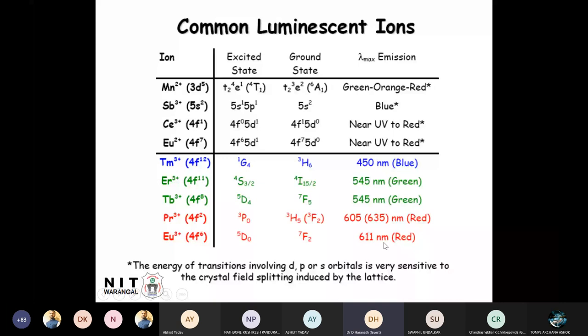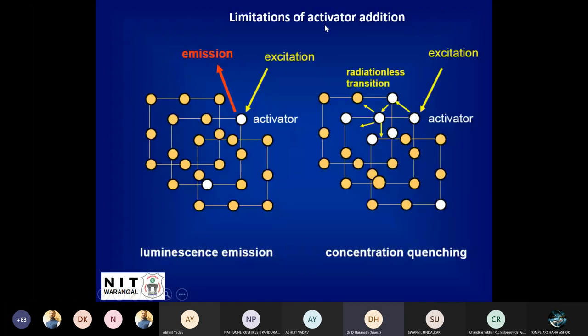Okay, and let me tell you much more in detail about this one. And how much activator we need to put, that is another question. Like in a crystal, if you are adding an activator ion and it is substituting one of the sites, slowly if I add more and more activator, it will replace many of these sites, is it not? So how much do I have to put? See, if you put very little, then the photoluminescence emission will be a little weak. But if you start adding more and more activator, your spectrum will be much more intensified. Okay. And after a while, you see that the intensity again drops down, even though you are increasing.